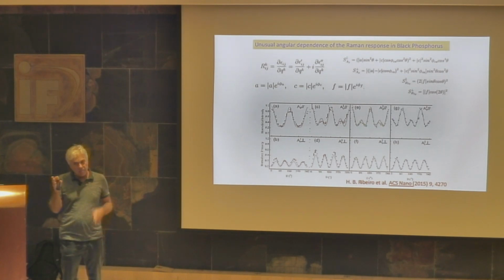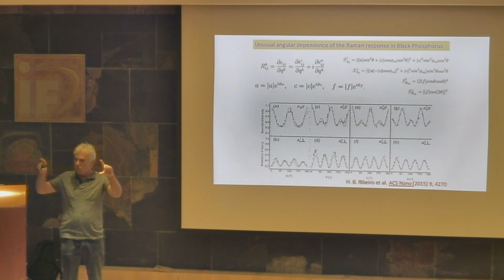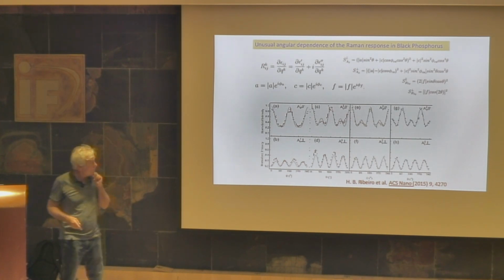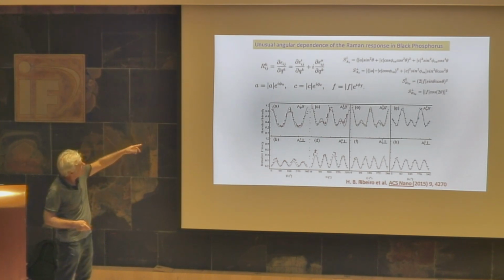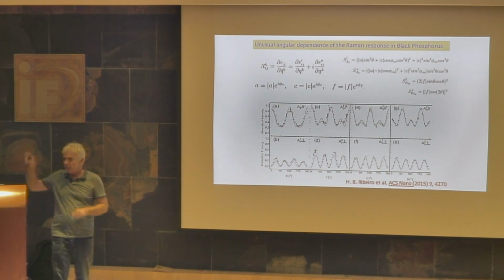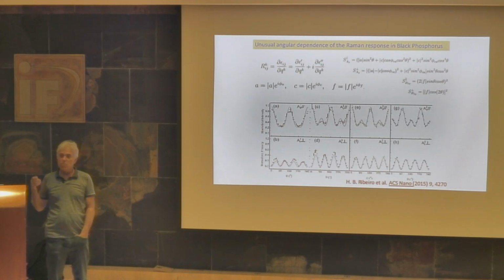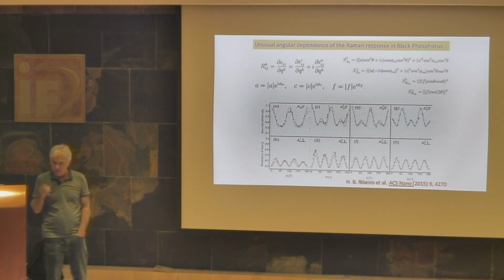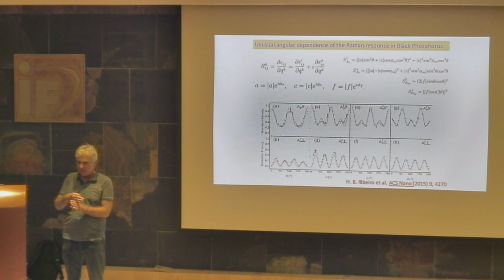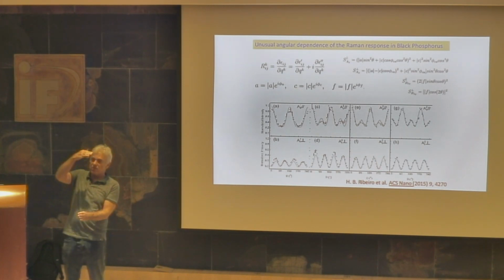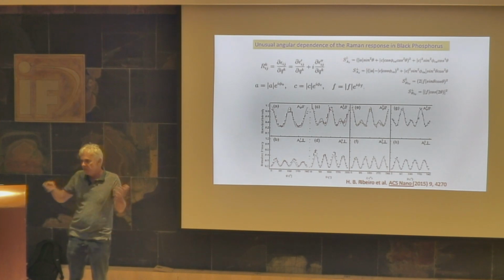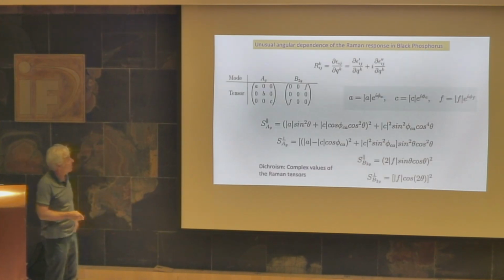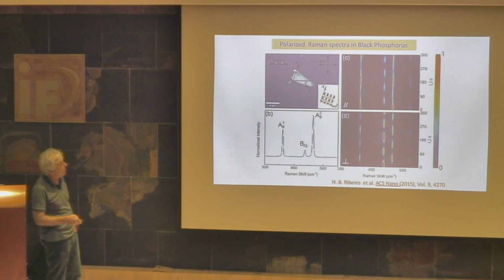I'm not sure about tin sulfide, but I know that germanium selenide and germanium sulfide have this orthorhombic structure. Okay? Then they have the same kind of behavior. But when you have an anisotropic crystal, you need to do polarized Raman. If you do Raman without taking care of the polarization of the scattered and incident light, we can get some result, and that's what we get normally.